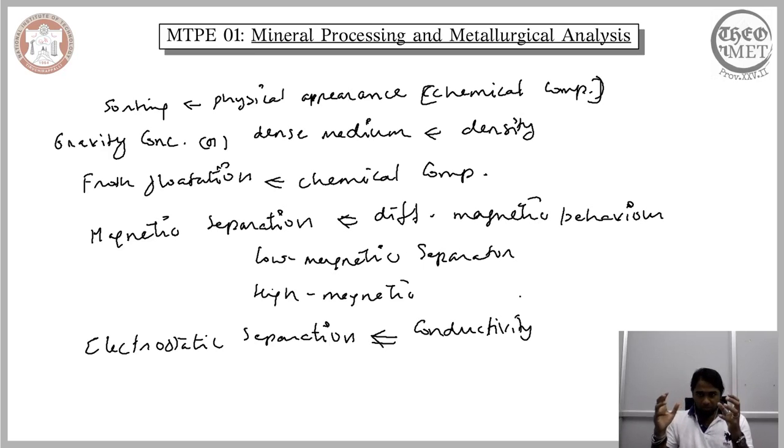Again, what the process of comminution renders us is a mixture of different particles with varying proportions of our concentrate and the gangue mineral. Because the desired mineral exhibits a different level of electrical conductivity compared to the gangue, we can distinguish the concentrate from the rest by understanding how electrically conductive a given particle is. Supposing the desired mineral is highly conductive, the conductivity would vary depending on the amount of this mineral present in the particle. When a particle is highly conductive, it predominantly comprises our desired mineral, and as the conductivity decreases, the amount of the desired mineral is also decreasing.